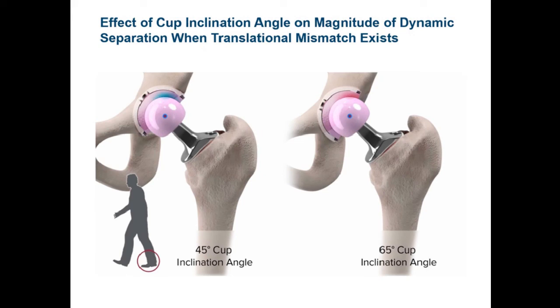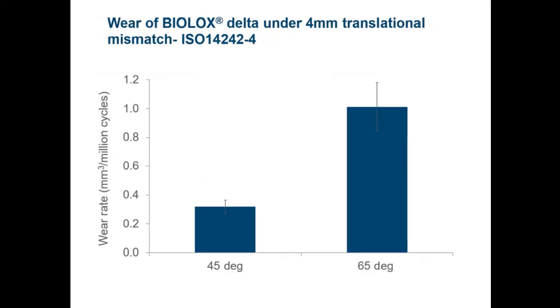So such combinations of different scenarios would lead to different tribological conditions, and as well as improving on the material properties, we should improve on surgical techniques and positioning of these implants. And you can see with this example of in vitro studies that the wear rate of ceramic on ceramic bearings with a 4 millimeter mismatch with a 45 degrees inclination angle produced a wear rate of 0.3 millimeter cubed. But if you apply that 4 millimeter mismatch with a 65 degrees inclination angle, you increase the wear rate to almost 1 millimeter cubed per million cycles, a significant increase in wear rates.